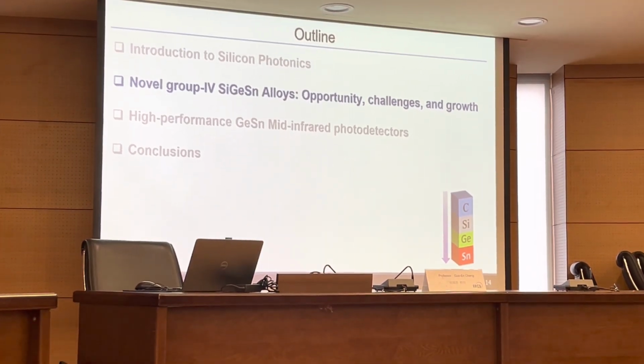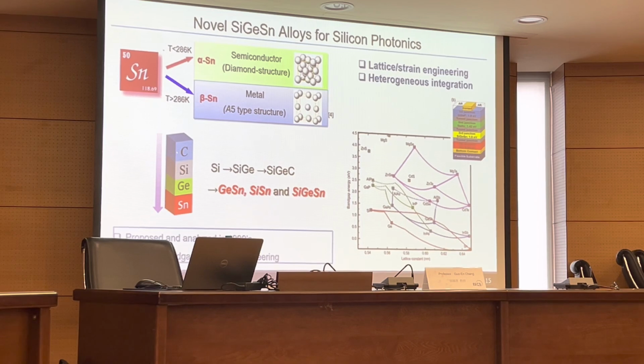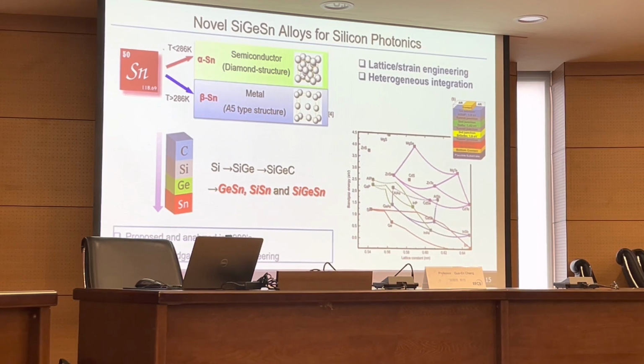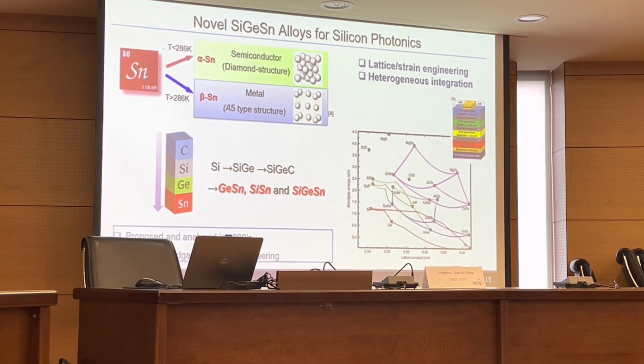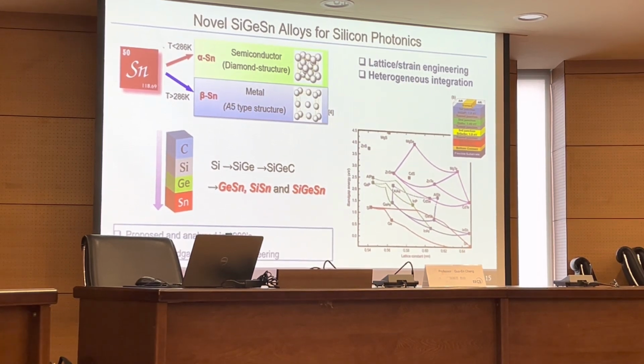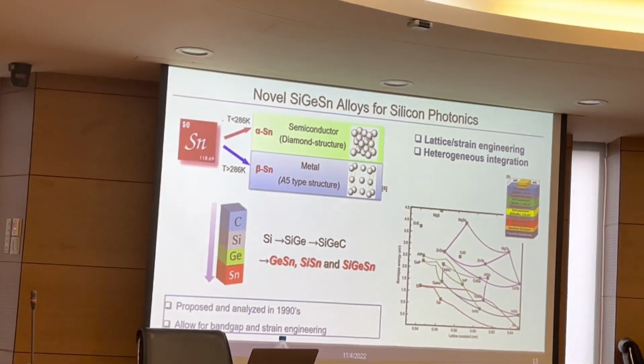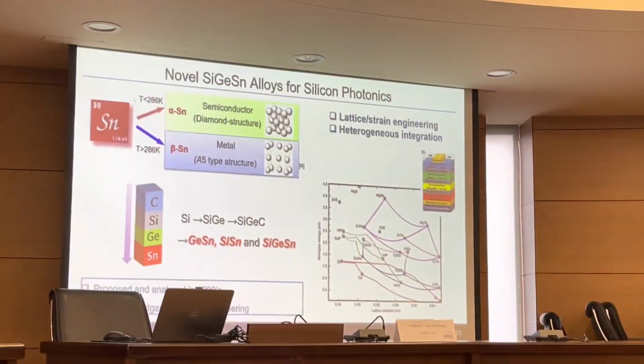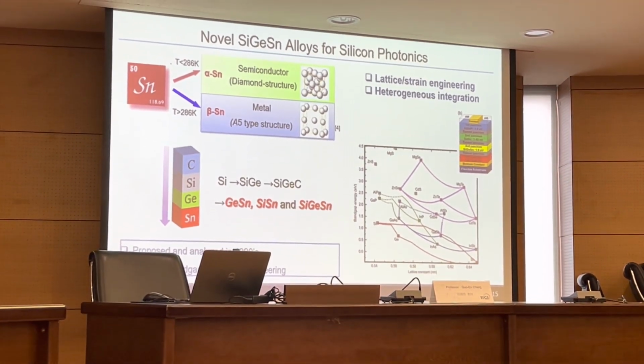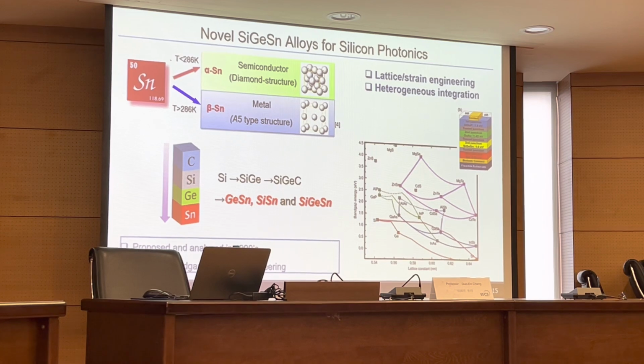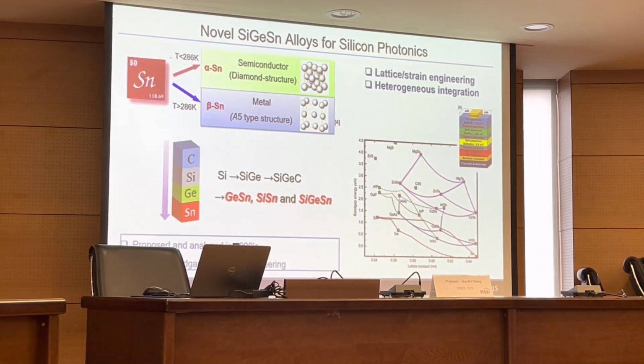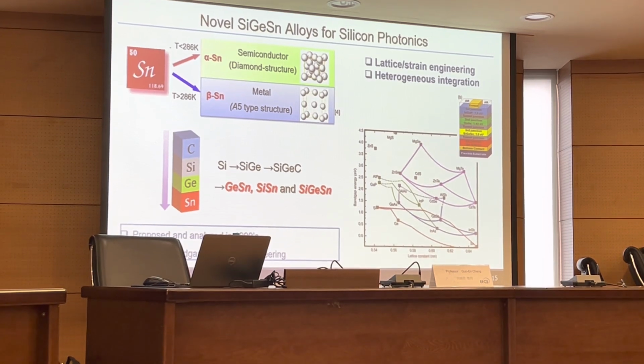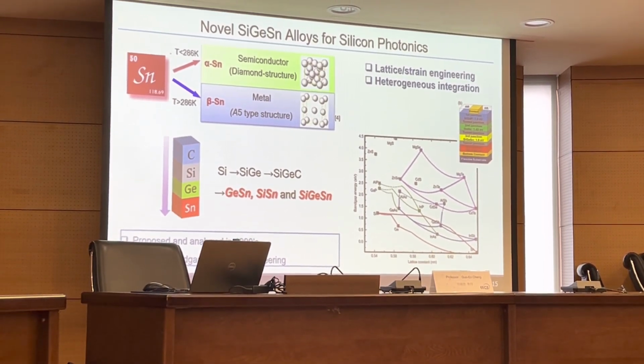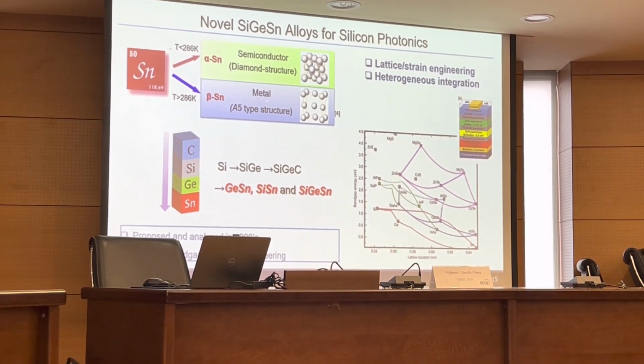The opportunity is to use a new material system: silicon germanium tin. Looking at column 4 elements, in addition to carbon, silicon, and germanium, there's another element, tin. Tin has two types: below 286 K is alpha tin, which is actually a semiconductor, and above 286 K is beta tin, which is a metal — this is the material used for welding, a very common material.